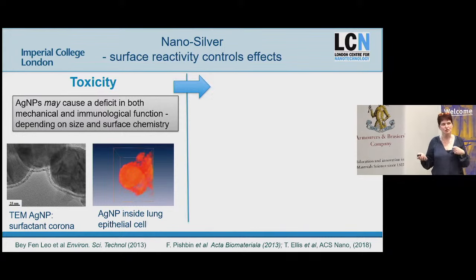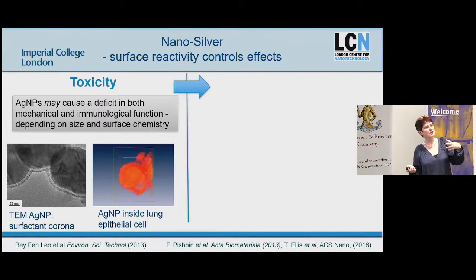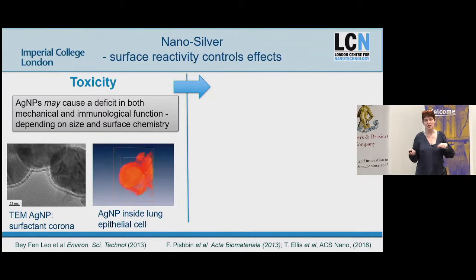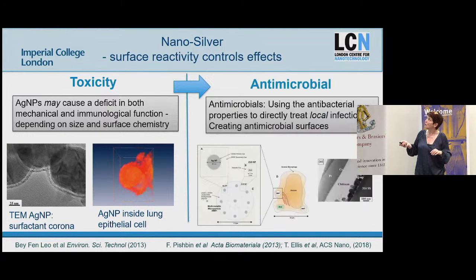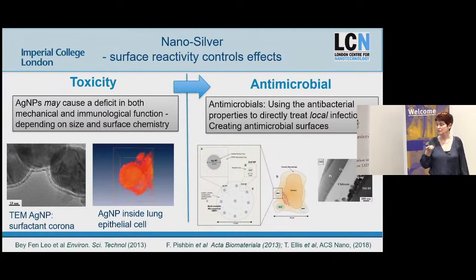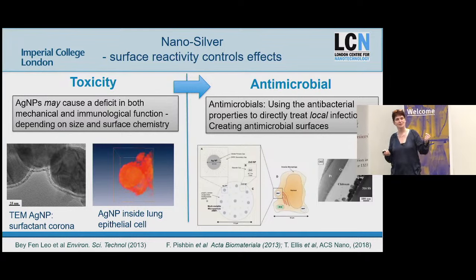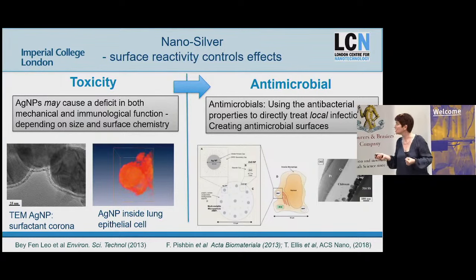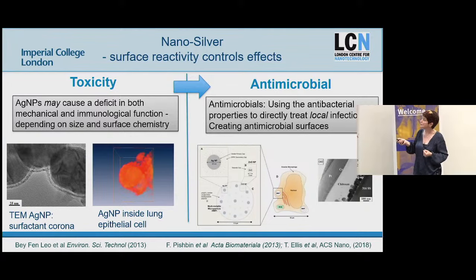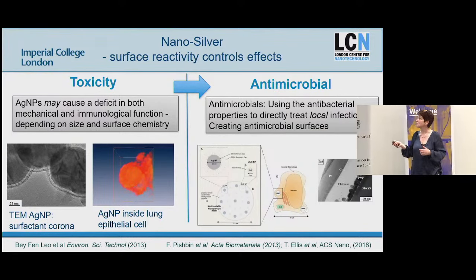So silver is not overtly toxic in the lung, right? But it can change the lung function if you're compromised, which is a really important result. But we also know that silver has a very strong antimicrobial nature, and we can use the same approach we just did with zinc oxide. We can take the silver nanoparticles and deliver them locally. Tim Ellis was able to show that you can wrap silver nanoparticles in plastic and deliver them into the lung to treat TB and other bacterial diseases very effectively, and combining that with conventional antibiotics causes an increase in cell death. Or you can incorporate nanoparticles directly into coatings on surfaces to make your surface antimicrobial.